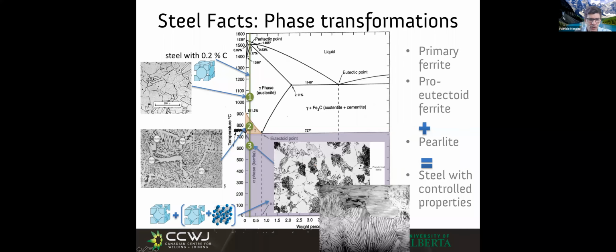Now, what used to be austenite, some of the austenite transforms into ferrite, and when I reach this temperature, which is called A1, that's the name people use for this, there is a temperature below which you can have no austenite at any composition. So when I'm right before crossing this line, I have ferrite at this composition and austenite. I can use the lever rule and see, I have so much austenite, so much ferrite. But as soon as I cross this line, the austenite is unsustainable.